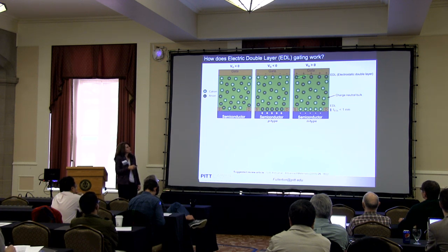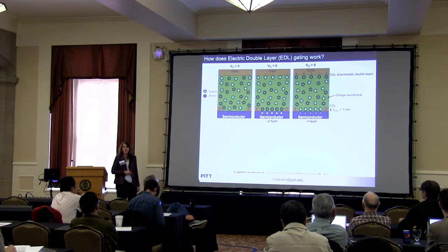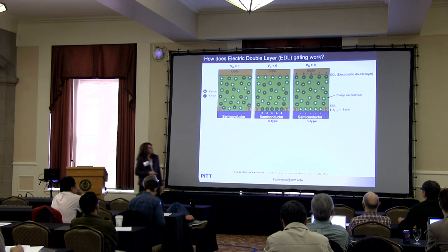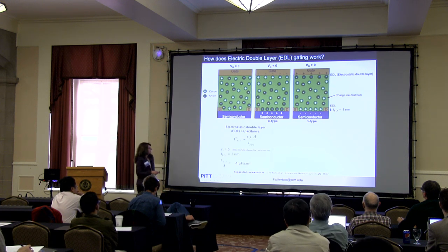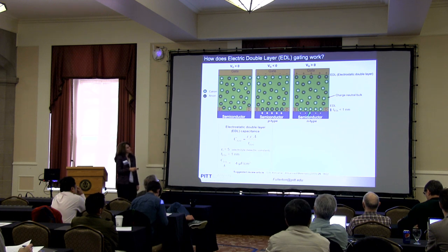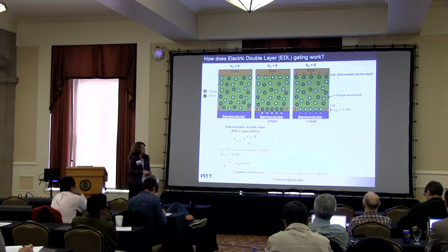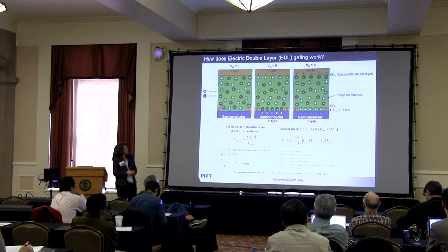And it turns out if you take a really short chain bit of polyethylene oxide and you covalently bind the ends together, you get this thing called a crown ether ring. And the crown ethers like to solvate metal ions. So if you look at a side profile, the ring's kind of flat. And you can imagine if you apply an electric field, you might be able to push the lithium ion to this surface, creating a low resistance or on state,